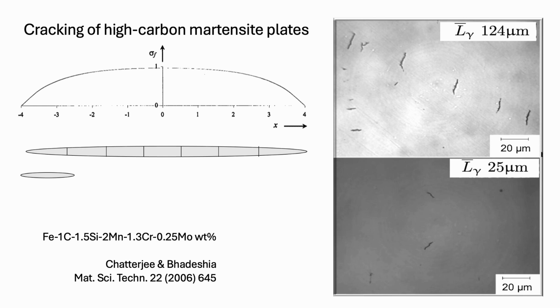So what we want to do is to create an austenite grain size which is finer than the distance between these periodic cracks in martensite plates. So how do we do it? How do we make an incredibly fine austenite grain size of something like half a micrometer? That is a ridiculously small austenite grain size.